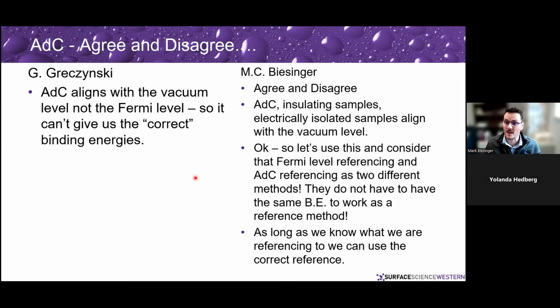So if we float the samples, you're going to use adventitious carbon as your charge correction. If you have a metallic peak in there, it may not be exactly where that metallic peak is there, because this is not the same referencing system, but we don't have really an alternative.